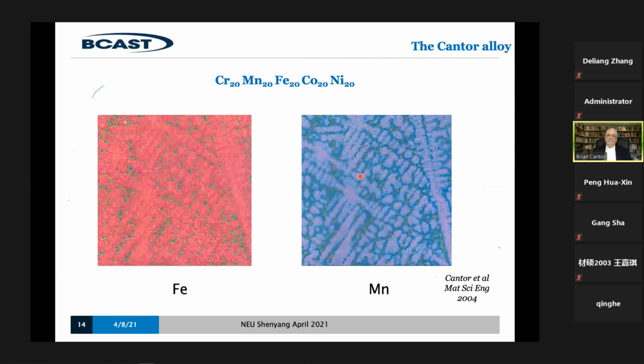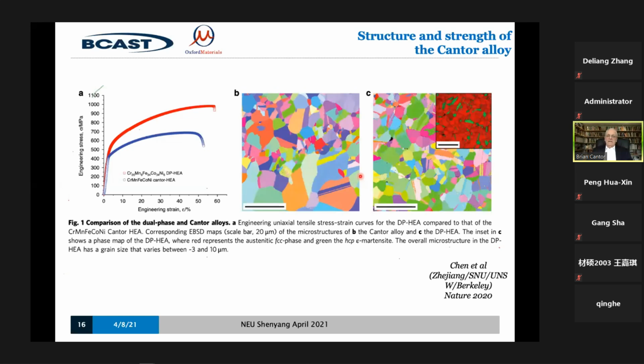And it's soft. It's like all face-centered cubic materials. If you can forge it or you can roll it and deform it, and then recrystallize it by heating, you get nice equiaxed microstructures like this. It looks exactly like the pictures before with dendritic structures from the casting, which is what you would get with copper or gold or aluminium, pure aluminium. But when you recrystallize it, as you would do with copper or gold or aluminium, you get equiaxed microstructures like this, with the occasional annealing twin.